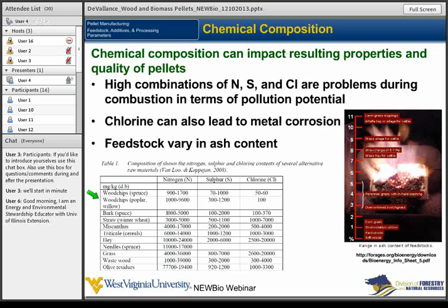One big thing that we measure, in our case using an ultimate analysis test, is how much ash content there is in these materials. If we look at hardwoods and softwoods, they can be 1% and below. You can get over 1% in some cases, especially once you start adding bark in, then you're getting a lot higher in terms of ash. So if you're producing wood chips and you're not debarking the logs really well, then your ash content can go up. We really look at debarking logs as something that plays an important role in the ash content. If we compare that to, say, perennial grasses with in-field leaching, 3 to 5% ash content, or switchgrass, which is around 3. So wood, in terms of ash content, is relatively low compared to some other biomass materials.